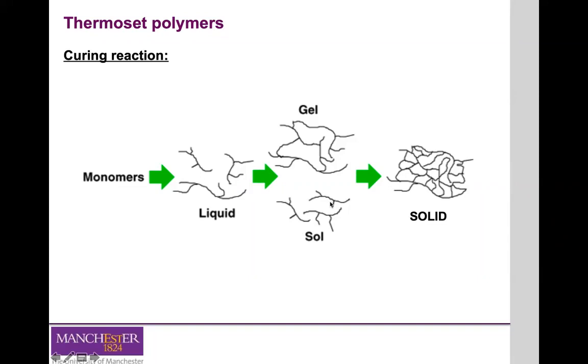The sol phase can still be removed at the gelation stage because it's not cross-linked. So we can use a solvent to remove this material that has not yet reacted, but the gel is insoluble, okay? So we cannot break these bonds and reuse the material. If you continue to apply energy to this system, you'll force these monomers and photoinitiators that have not yet reacted to react and assemble into a three-dimensional solid network, where in theory all the monomers react and form polymeric networks. This is not always the case. You don't always obtain a 100% curing reaction, or in other words, not all of the monomers will react and form a polymeric chain. There is always a small percentage of monomers that will not react and will then be removed.